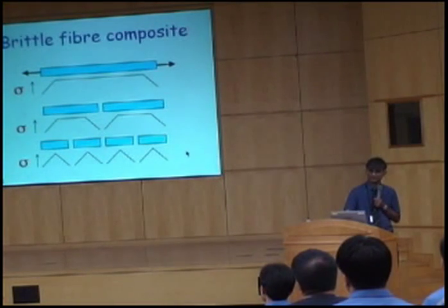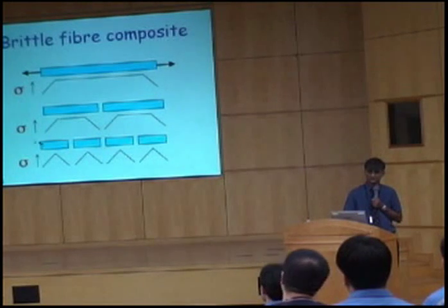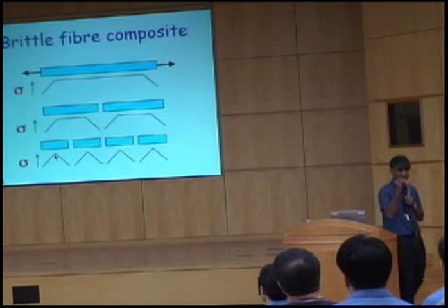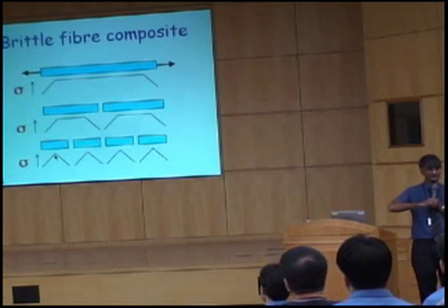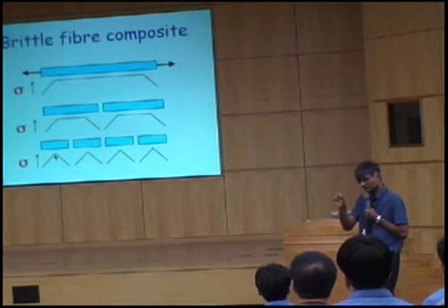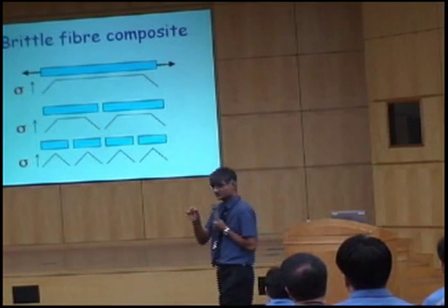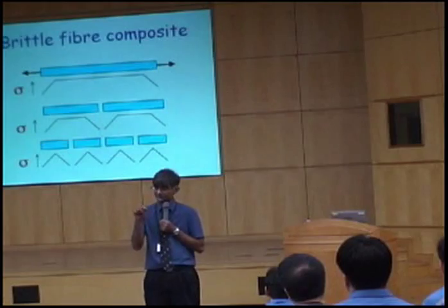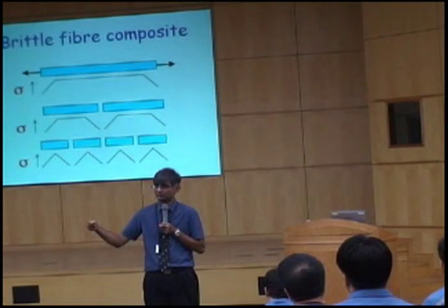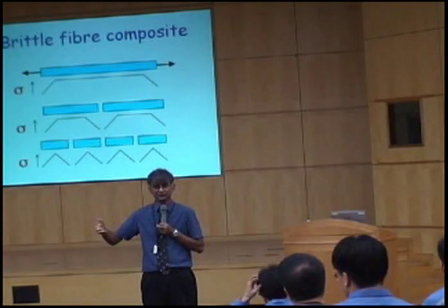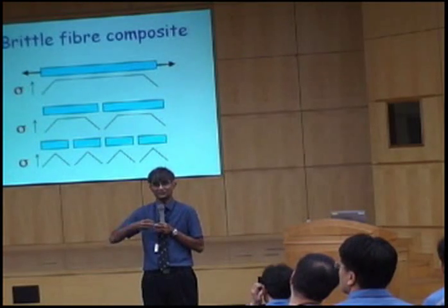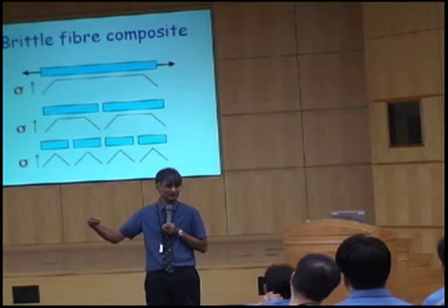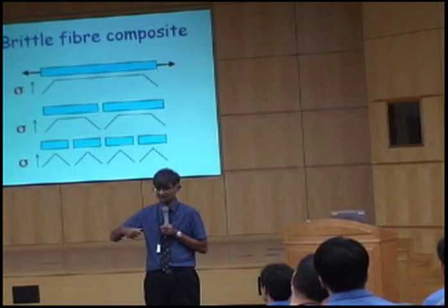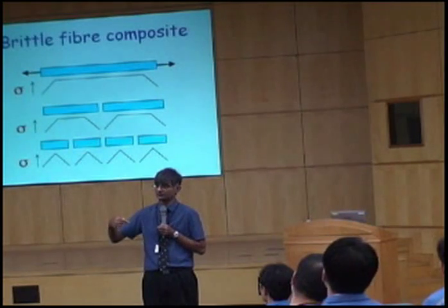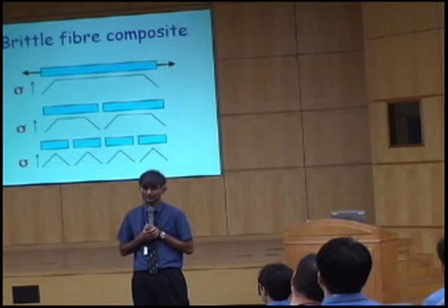And you get to a point where after you apply the stress, these fibers will not break because the peak value of stress reached inside the fiber is now less than the fracture stress. So if you make your glass fiber smaller than a certain size, which depends on the characteristics of the interface between the polymer and glass, then it will not break when you pull it. Of course, it doesn't make your composite strong because you need the fibers to carry the load. But if they are smaller than a certain size, they will not break because you cannot transfer stress from the polymer to the glass fiber.